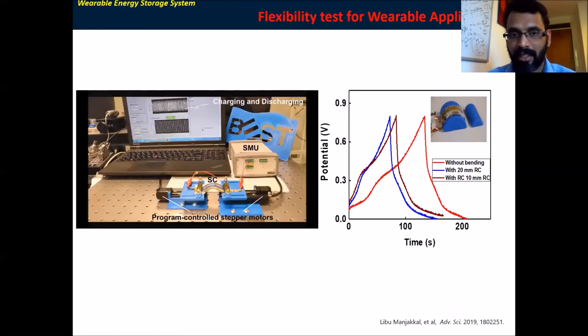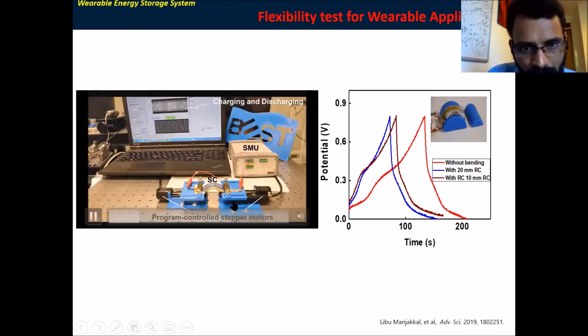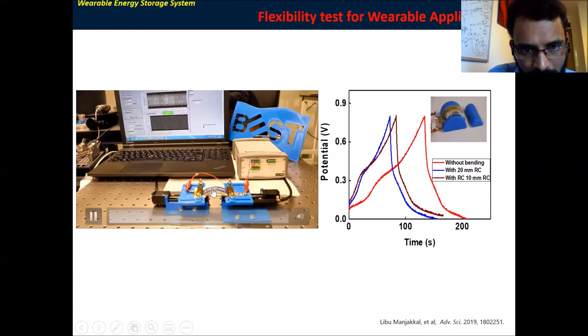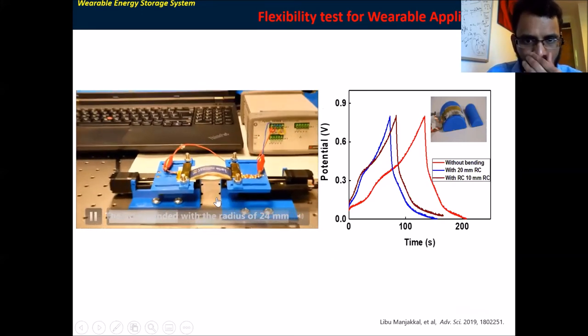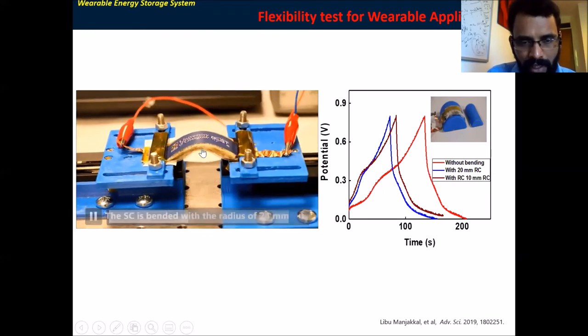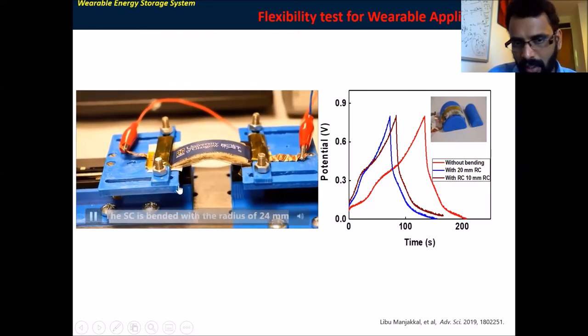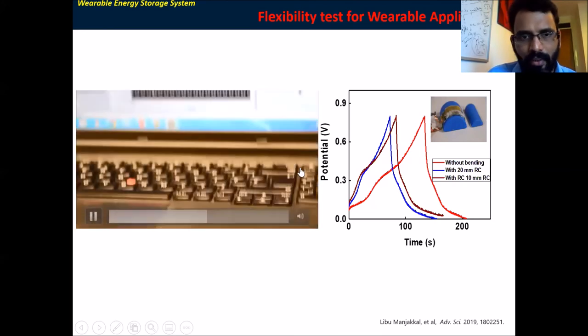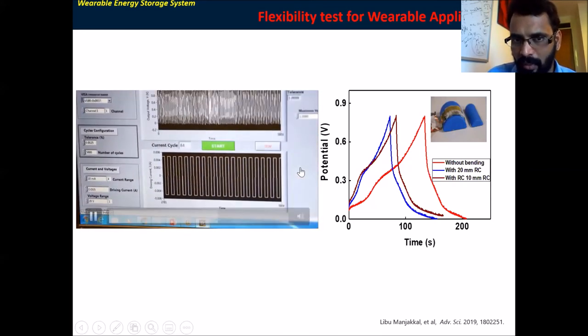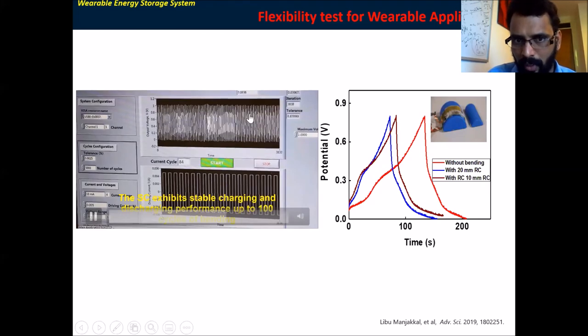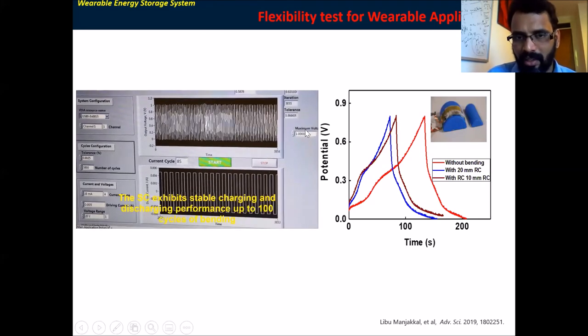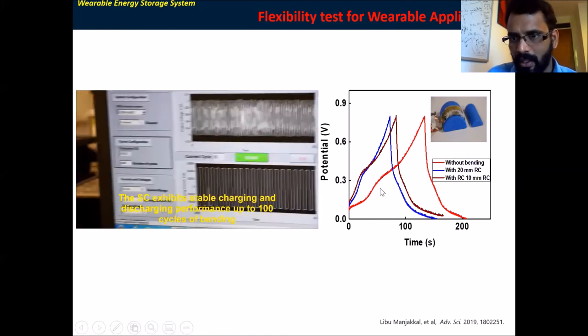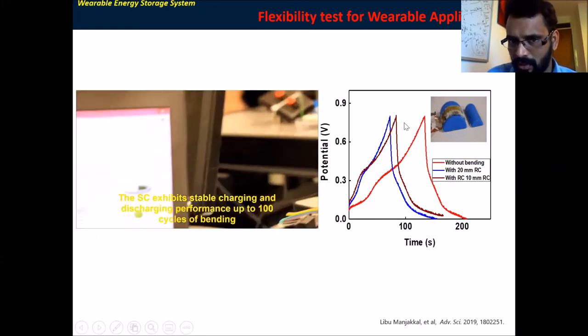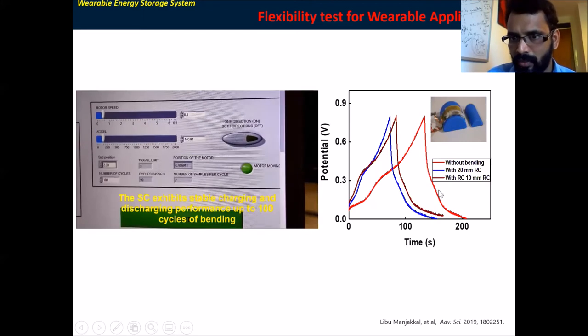Then in a wearable application, another important point is that we need to measure the cyclic bending, a dynamic or static bending. You can see here, we attached the supercapacitor to a fixed plate, and then it's moving. During this cyclic bending, you can see the charging discharging analysis, with almost 24 mm radius. We bent the device for a continuous 100 cycles. I noted that there is not much difference in the performance, almost the same performance. So the cyclic bending is not affecting our device. And I also carried out the normal bending, as you can see here, at 20 mm radius